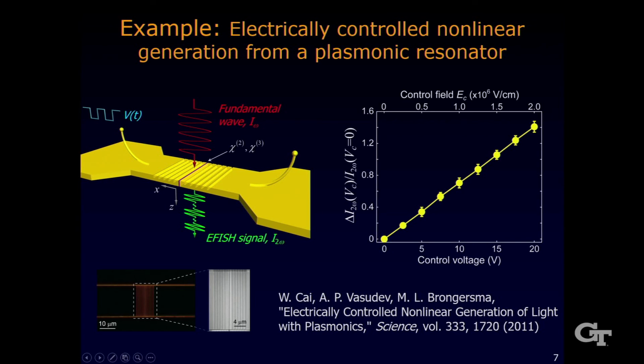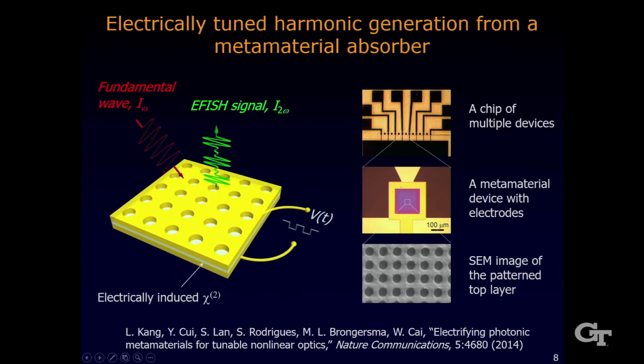Okay. And now something newer. In this part, we are trying to demonstrate the electrically controlled harmonic generation of light from a metamaterial platform. Especially here, we have a so-called metamaterial absorber, which you can see has periodic metallic structures, the whole array in this case, separated from a backplane by a dielectric spacer. Then you apply a voltage to enable the effective chi 2 response, and that can control the harmonic generation from the entire system.